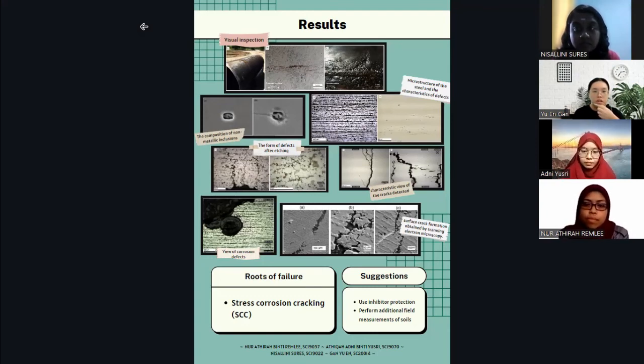In conclusion, the predominant mechanism for the formation and development of stress corrosion cracking is local anodic dissolution of the metal at the grain boundaries. This study indicates that the area of propagation of high pH stress corrosion cracking may be somewhat wider than previously thought. In particular, it can be associated with various anionic compositions of soil electrolyte and may proceed in different geological and climatic conditions. That's all from our group.